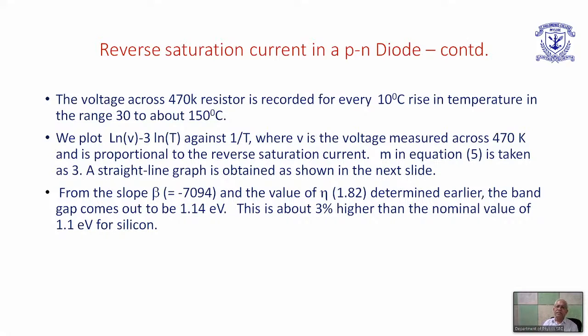The voltage across the 470K resistor is recorded for every 10-degree rise in temperature. The range of temperatures is from room temperature to about 30 to 150 degrees centigrade. Using this data, we plot natural log of bias voltage minus 3 times natural log of the temperature against 1 by T. We again get a straight line. It is shown in the next slide, but from the slope of the straight line, which is something like minus 7,000, the value of eta was found to be 1.82, and the band gap came to about 1.14 electron volt. So this is about 3% higher than the standard value for silicon.